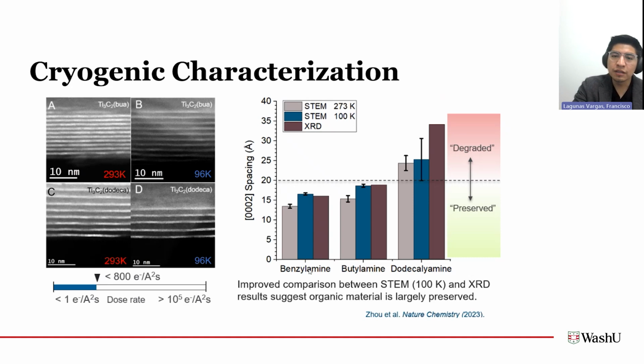And then in this dark blue color, we have the new measurement that we did using cryogenic STEM. So as you can see, there's much better agreement between the cryogenic STEM measurement and the XRD measurement compared to our original room temperature STEM. This method has its limitations.